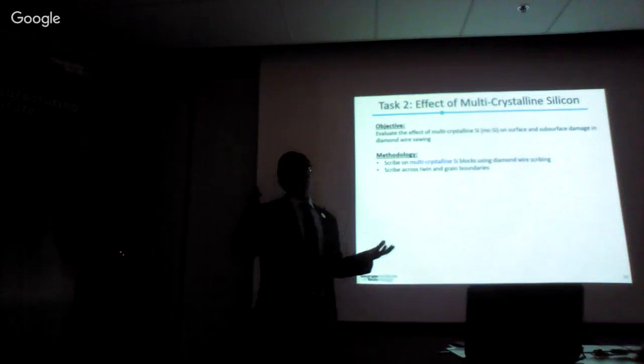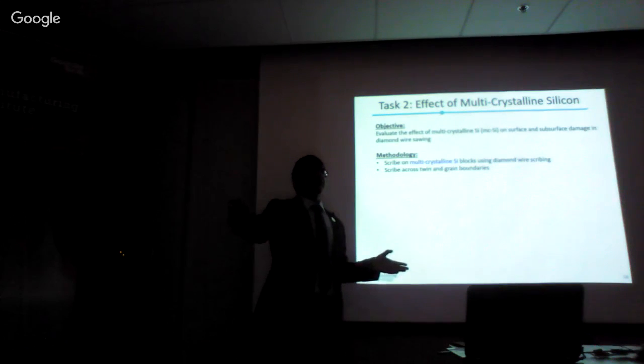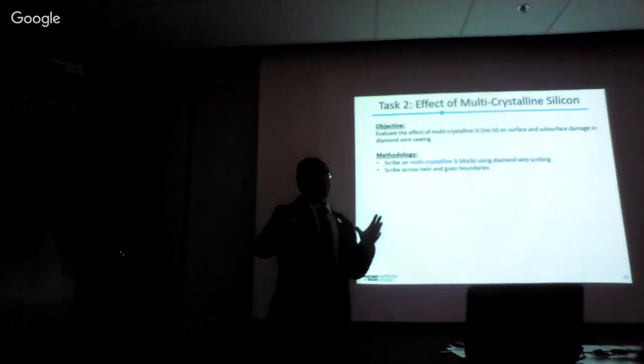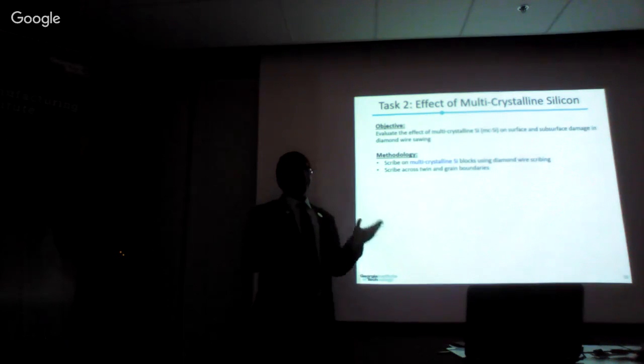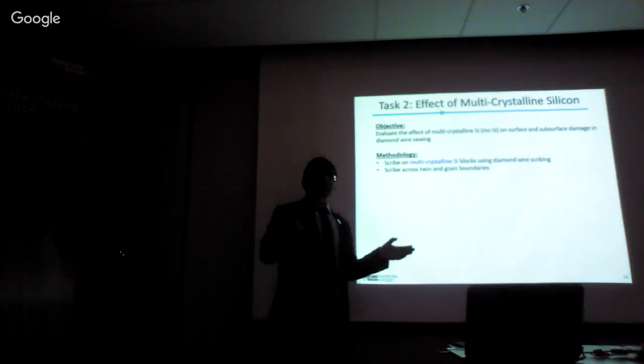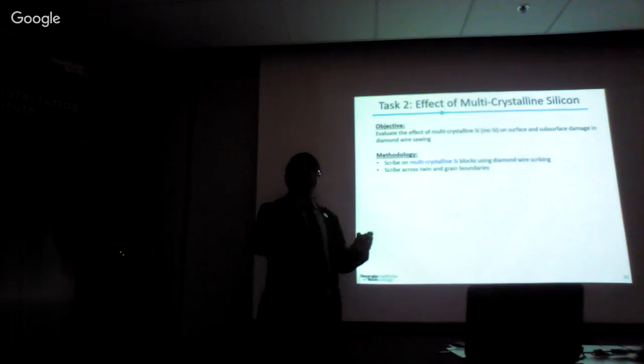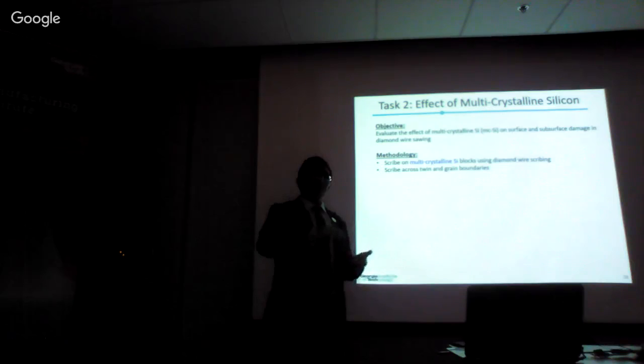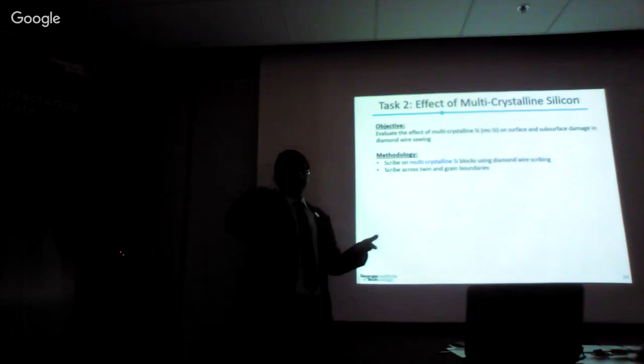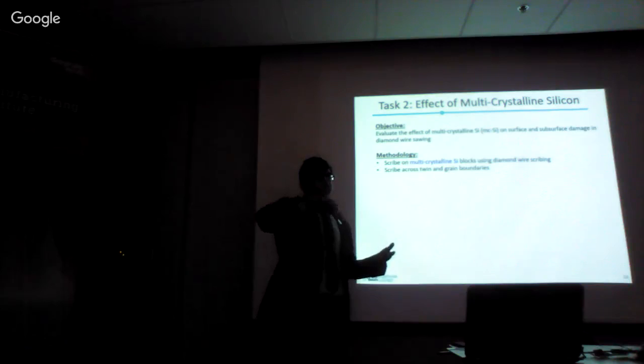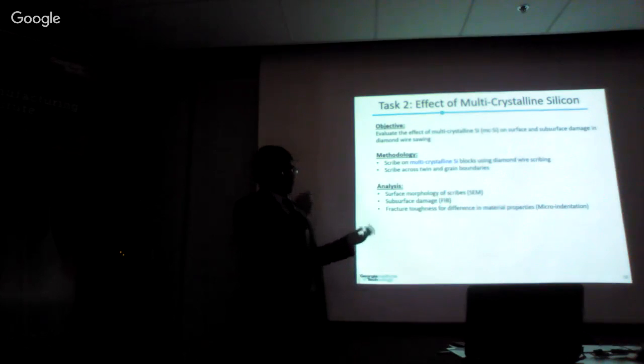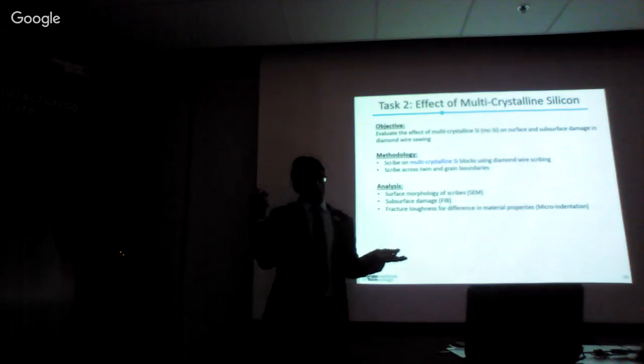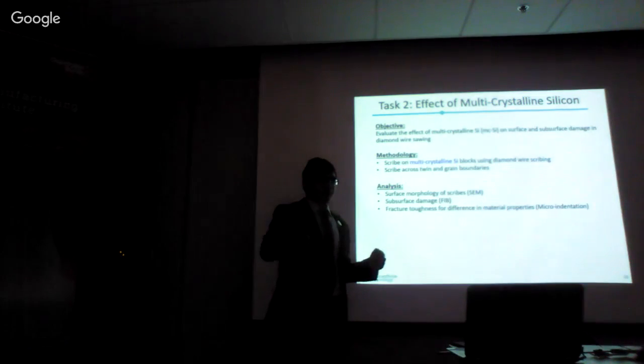Do note, here we are not using increasing depth of cut scribes because our focus is not on the shape of the abrasive or finding the critical depth of cut. Our focus is finding the effect of grain and twin boundaries, which is in the workpiece. So we are using constant depth of cut scribes. The depth across the different scribes is the same. We analyze the surface morphology by SEM. We analyze the subsurface damage by FIB, and for the multicrystalline silicon material across the twin and grain boundaries, we